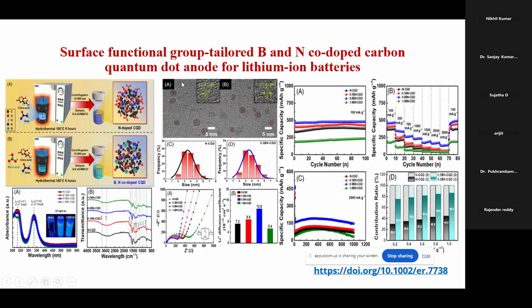Then, another work: people nowadays are working on carbon quantum dots with boron and nitrogen. I already mentioned my work. This is another work by other people on surface functional groups. Here they do functionalization at the surface level, and B and N co-doped carbon quantum dots are useful for lithium-ion battery anodes, made by normal hydrothermal at 180 degrees for 6 hours, then centrifuged at 10,000 rpm. Maybe we can do dialysis also.